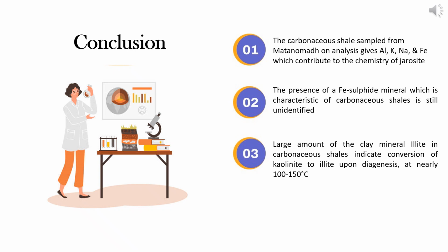Kaolinite starts to convert to illite when temperatures reach around 100 to 150 degrees Celsius, though this can vary depending on other factors such as the availability of potassium in the surrounding environment, burial depth, and fluid interactions.